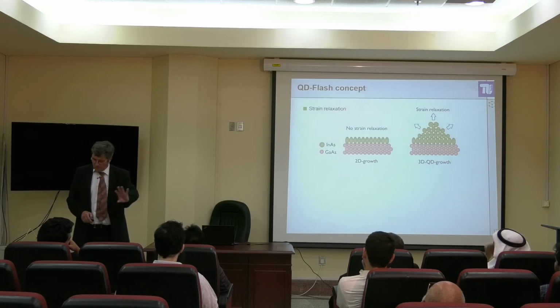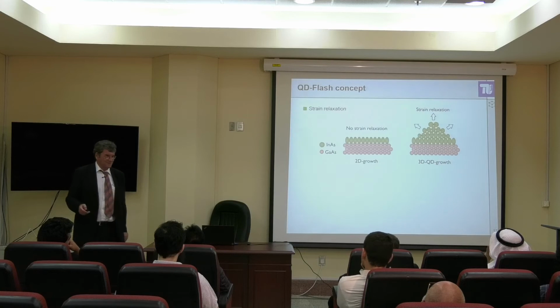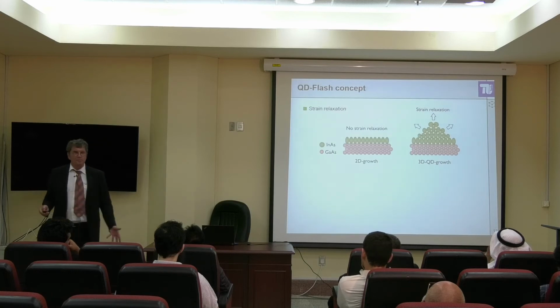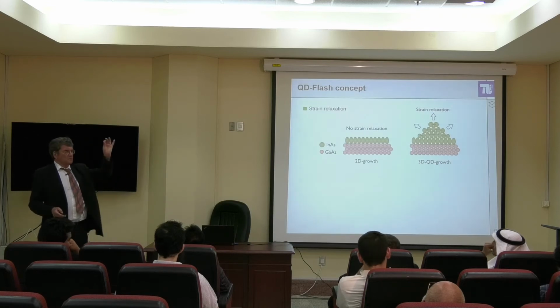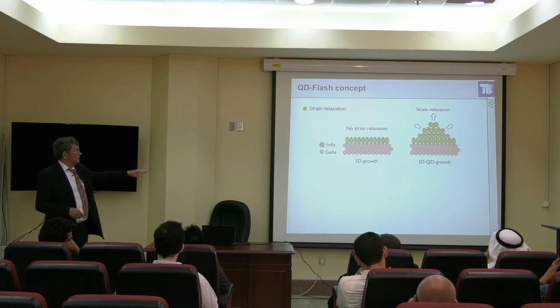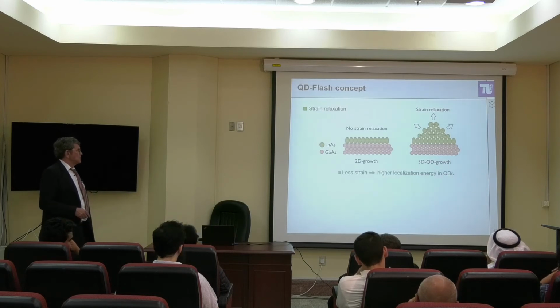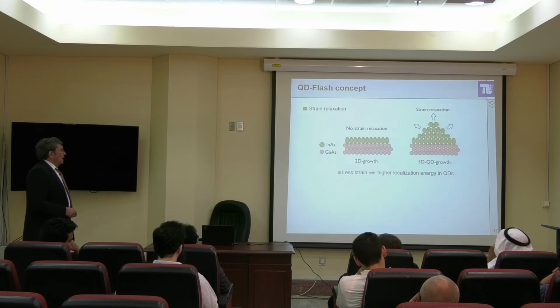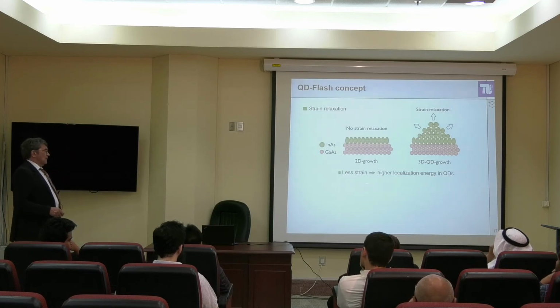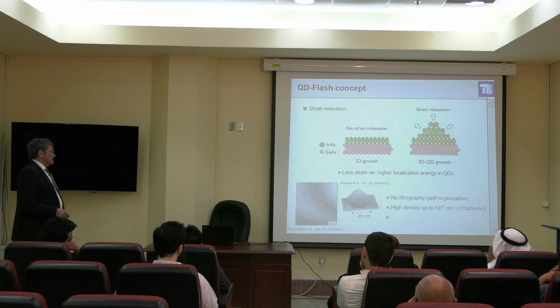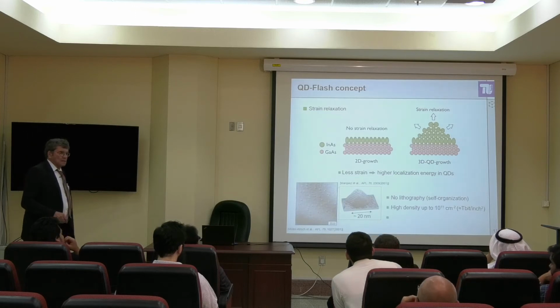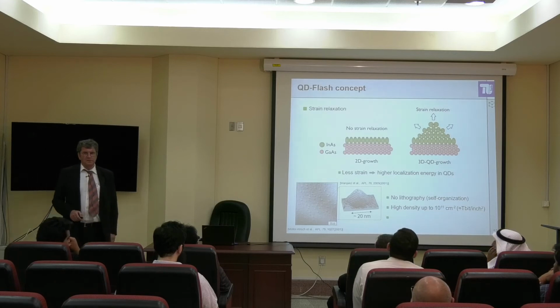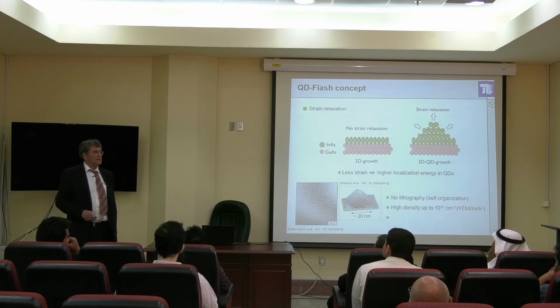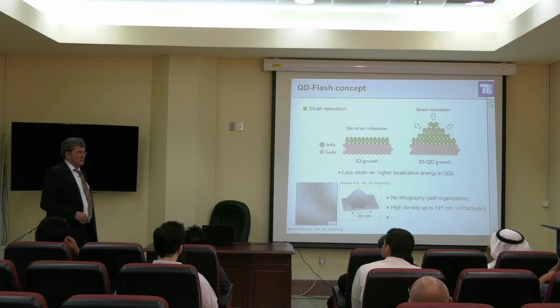No physicists around, so no question about this subject. First-order phase transition, that means just you release energy. By forming pyramids here, you release energy. Minimum energy. Less strain, higher localization energy in quantum dots, and here you see a three-dimensional picture. This picture was made with scanning tunneling microscopy in an MBE machine.